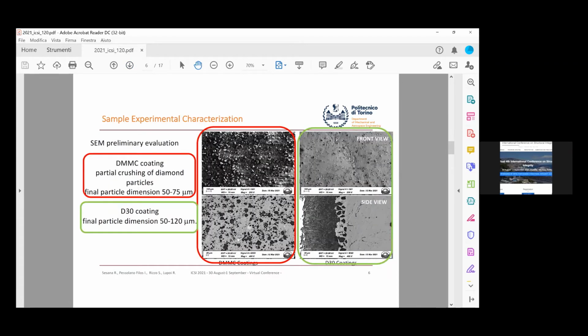Coated discs were subjected to preliminary evaluation by means of the scanning electron microscope, and the outcomes are displayed in the figure in the front view and in the cross-section view. Subsequent image analysis showed that in case of DMMC, the employed deposition process led to a partial crushing of the diamond particles, with their final dimension being comprised in the 50-75 micrometer range. By comparison, the D30 coating was found to be slightly coarser, with particle dimension comprised between 50 and 120 micrometers.